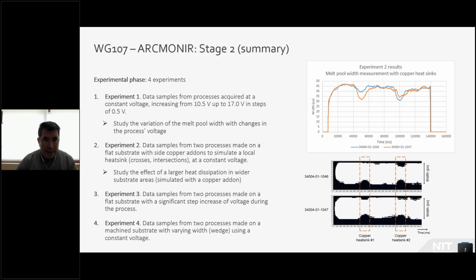So this is the result of this experiment. With the camera, we can see that the melt pool width is being reduced as we pass next to these copper heat sink areas. And here we can see if we binarise the image of the melt pool width with the time, we can see how the melt pool is stretching as there is a larger diffusion area.